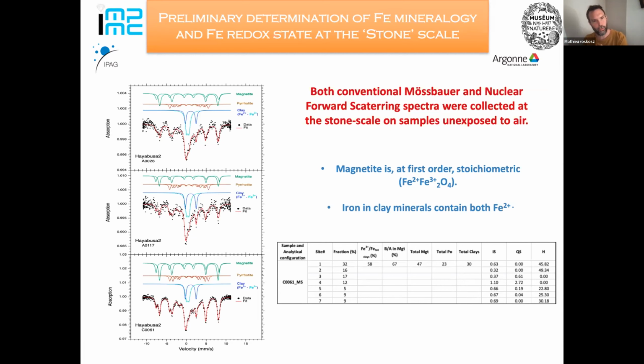But what was reassuring was the fact that taking just the model developed for grain 61, we were able to fit the data pretty well, just playing with the abundances of the different minerals. The first result that we were able to derive was that the magnetite at first order is stoichiometric, and the fact that iron in clay minerals contains both Fe2+ and Fe3+, which was already a very important result for us.